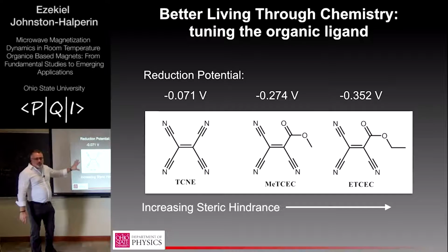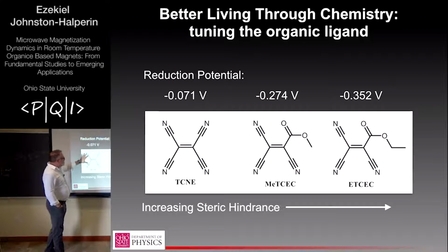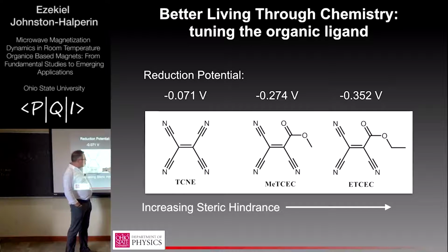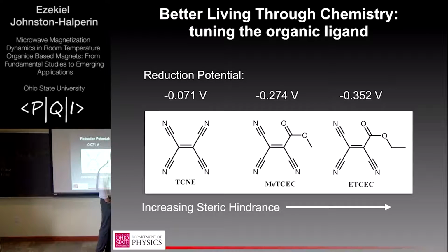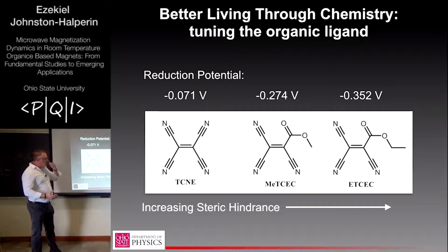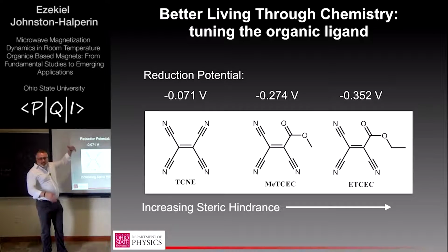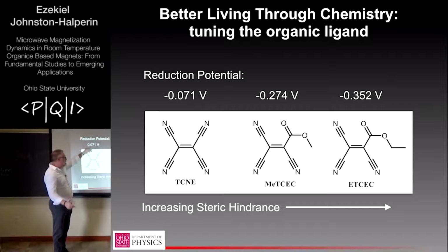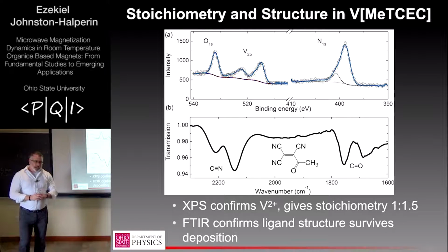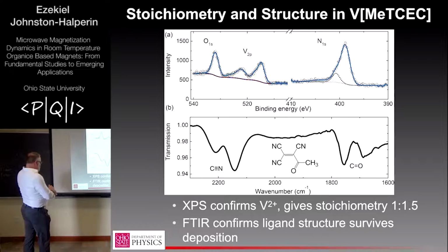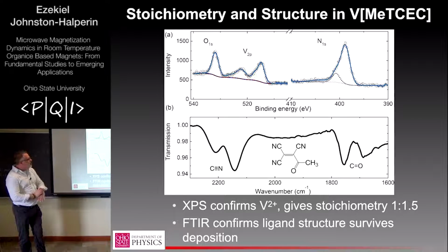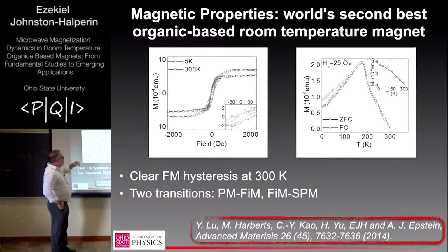This is sort of a more chemist's eye view of the material. So this is the parent compound, vanadium TCNE. I talked in the last section about this METCEC, where we add this functional group. With ETCEC, we make that functional group even more bulky and more electronegative. The reason we had those films in the first place, this anisotropy discovery, was basically serendipity. But we're interested in how the magnetism changes as we vary the ligand. This is just structural characterization to make sure we're still making a compound. And so here's the comparison.